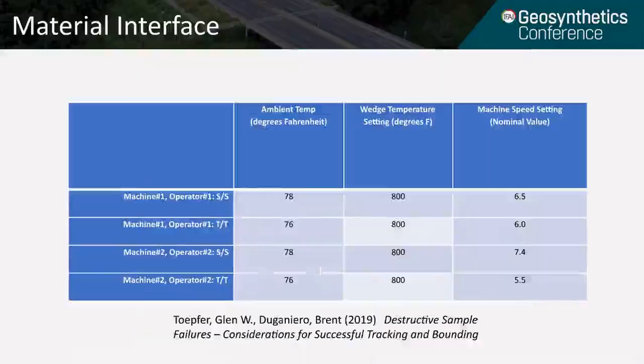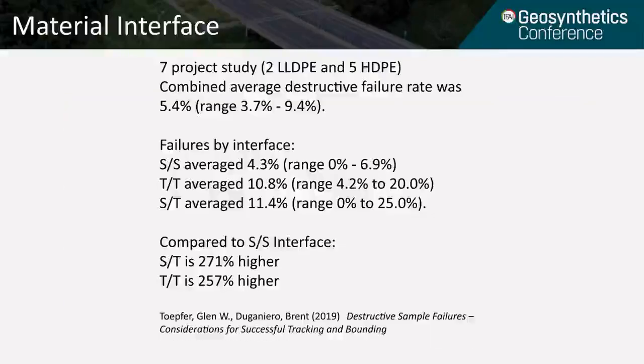between materials. And this table illustrates that there's different settings used for almost the same ambient temperature between machines and between interfaces, the predominant one being the speed was changed in this case. In a study that I participated in, we looked at failures by interface, and you can see smooth averaged 4.3%, but once you started getting the textured component added, the textured failure rates went up, and that's a result of the difference in the welding conditions changed by the texturing interface.